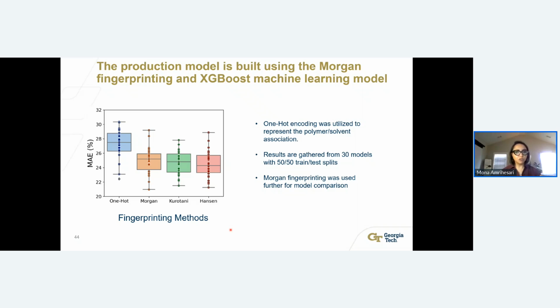It was not a Gaussian distribution between a large class of different functional groups. So we used one-hot encoding to just ensure that the model knows if the polymer is present in that solution or not. But for the solvent, the model is chemically aware of the solvent that it's dealing with. We were testing 48 solvents at the time that this study was done. So for that, we tested different fingerprinting methods to tell the model, based on the chemical structure or SMILES of the solvent, what are some of the characteristics that we can extract from the repository that is available, including RDKit.